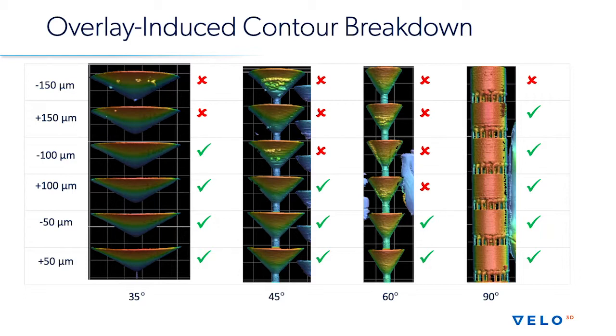And by forcing this specific offset in the overlays, you can see when the contours start to see these punch throughs and defects on different parts that indicate that the overlay is no longer good. And in this case, what you see is with a 50 micron offset in either direction, the contours remain stable. The process remains relatively stable. If you get more than that, it starts to break down. You start to get surface roughness, some contour defects that aren't acceptable.